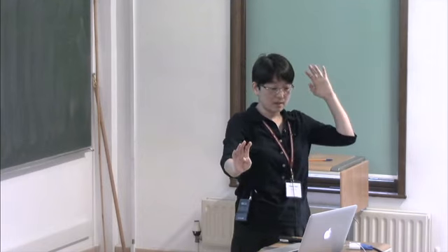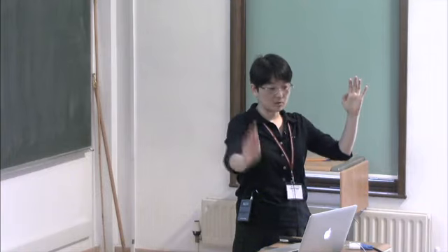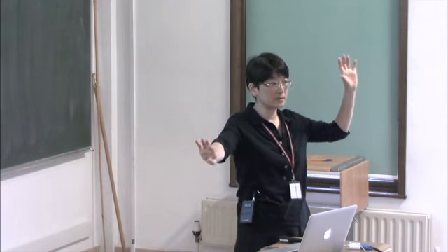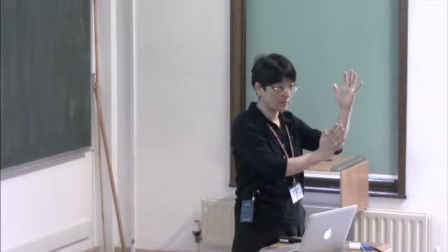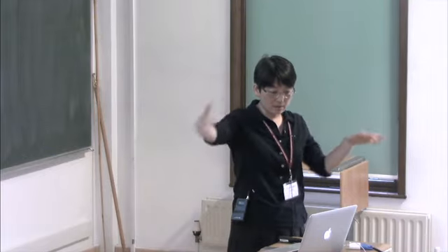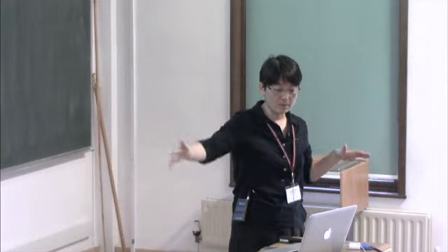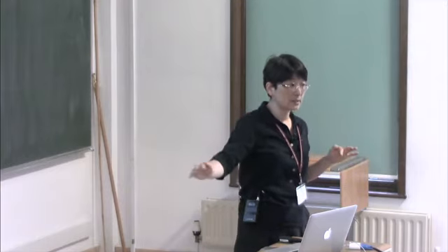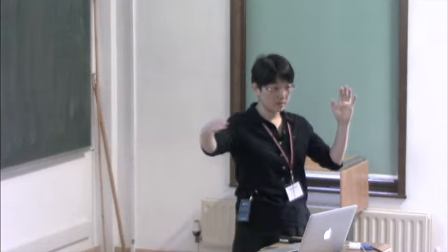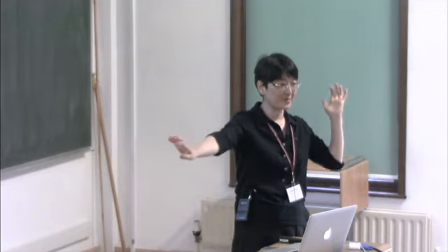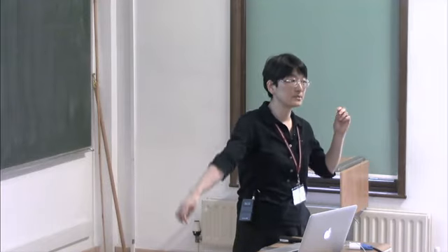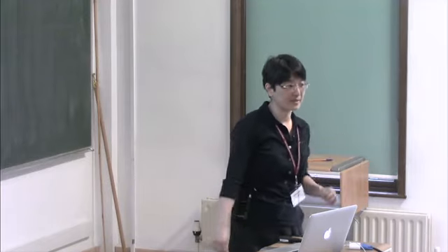So if the grain size is large, the shortest and the longest time scales are very different, but if the grain size is small, the shortest scale and the longest scale are similar. The broadening of the peak with increasing frequency, I think, is because the broadening of the spectrum occurs because of that wide range of time scales.